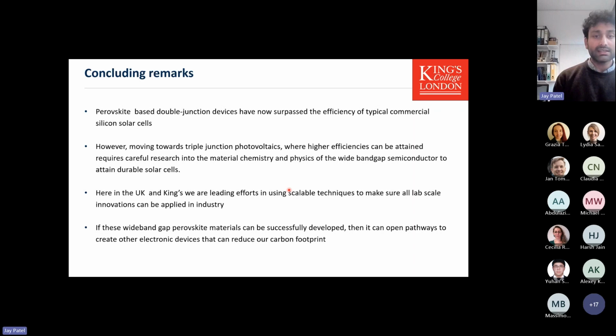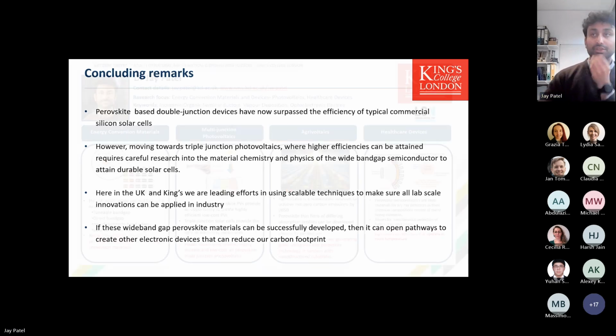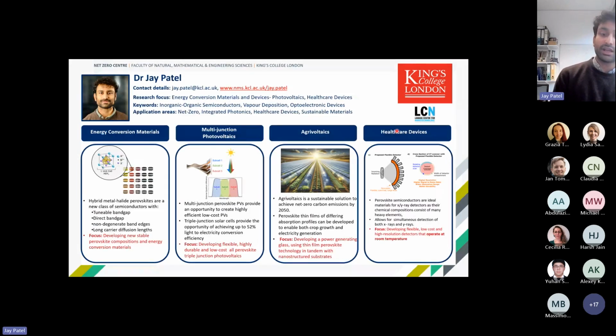One thing to note here is, as we develop this material, we found that it can be used for an array of different applications. One example is healthcare devices. Healthcare devices require a material that has a high Z number, so lead, cesium, iodine. It absorbs a lot of the X-rays. And because we can tune the band gap, we can make a detector that operates at room temperature.